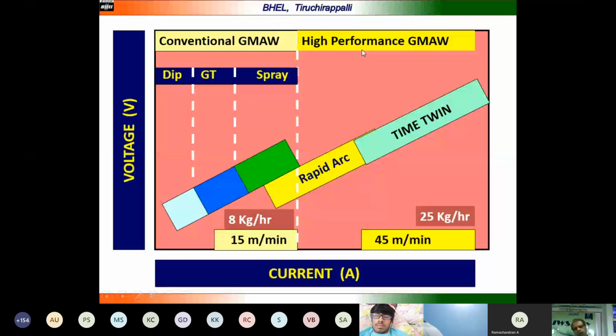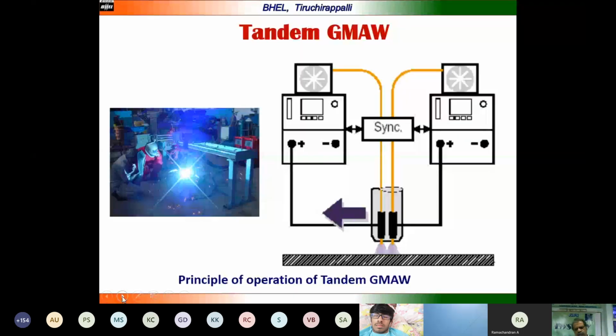Even the deposition rate can go up to 25 kg per hour very easily with this process. And this is a tandem GMAW process where you can see two welding wires coming from two different power sources, a single torch, and then the welding can be done very easily. Because of using the two wires in the torch and using the same weld pool to deposit the weld metal, the deposition can be almost double, or 68% higher productivity can be achieved. There is a synchronizing system available to see that the feeding is going right and the welding can be done in a better way.